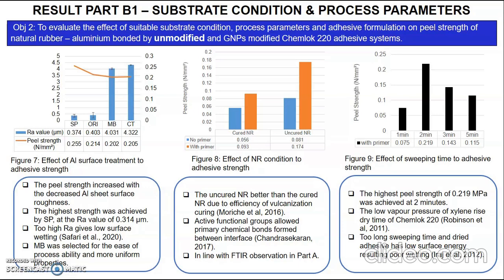And mechanical blasting was selected for the ease of processability and more uniform properties. Figure 8 shows that uncured natural rubber is better than cured natural rubber due to vulcanization occurring. And the effect of sweeping time shows best at 2 minute sweeping time. Too long a sweeping time and the dry adhesive has low surface energy, resulting in poor wetting.